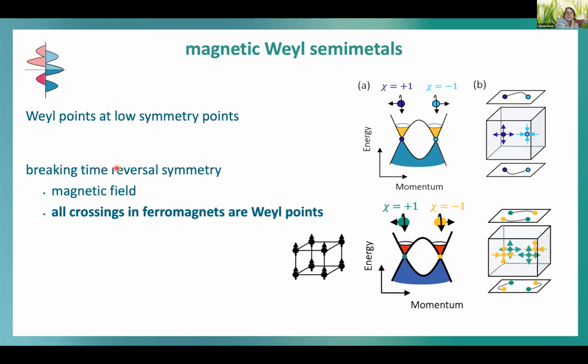Okay, then the next step was to add magnetism to the Weyl semimetals. This is very interesting because if you break time reversal symmetry, which means when we apply a magnetic field, for example, to a Dirac semimetal, we turn Dirac points into Weyl points. This is why Dirac semimetals show similar properties as Weyl points. But the Fermi arcs and the distance between the Weyl points are not so large. But if you have an intrinsic magnetic field, like in ferromagnets, all crossings in the ferromagnetic band structures are Weyl points. So it's only the question of how to get them to the Fermi energy, because the distance between these Weyl points can be much larger than if we simply break time reversal symmetry.